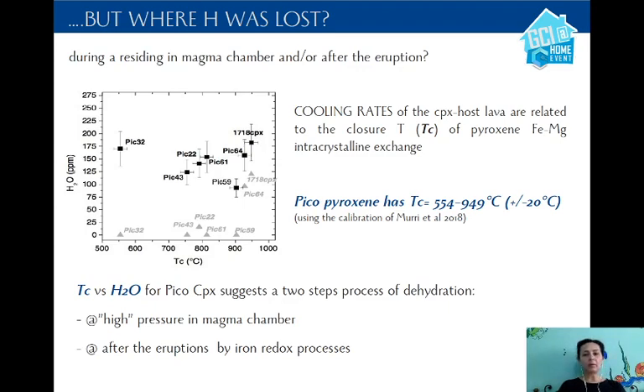estimated the closure temperature of pyroxene iron-magnesium intracrystalline exchange, because this temperature is related to the cooling rates of the clinopyroxene host lava. And as is reported in this plot, there is some correlation between the hydrogen, the water content recovered in our clinopyroxene and the closure temperature. So we suggest that the dehydration process occurred in 2 steps. One at high pressure in a magma chamber, and a second one after the eruption by iron redox processes.